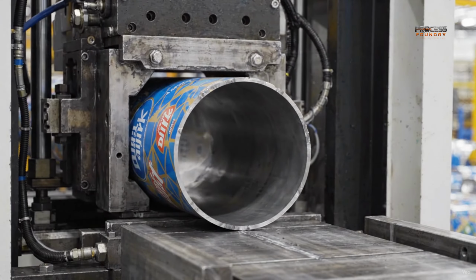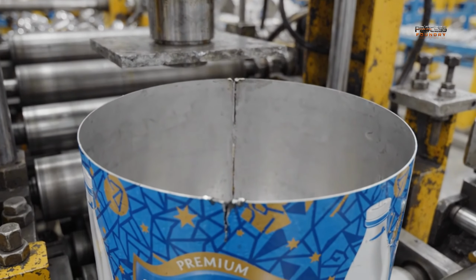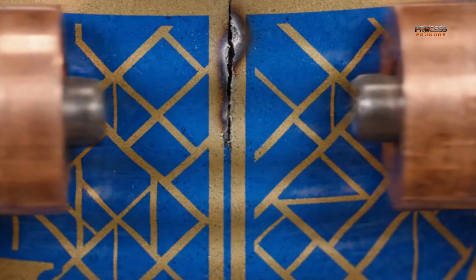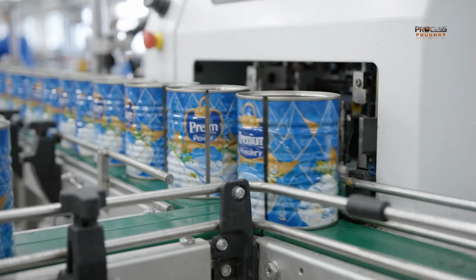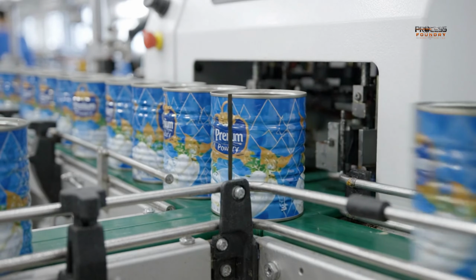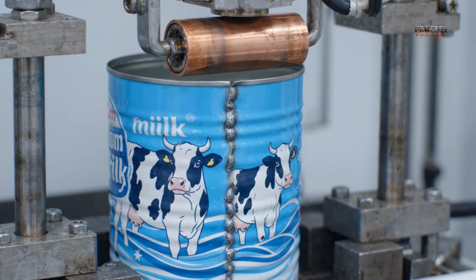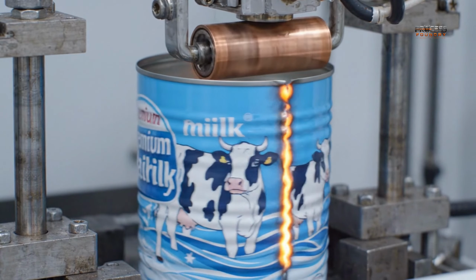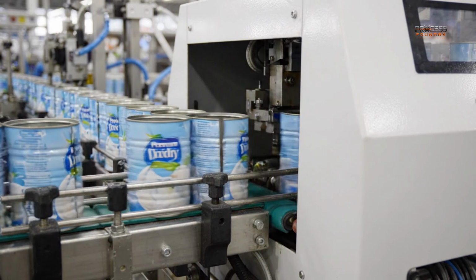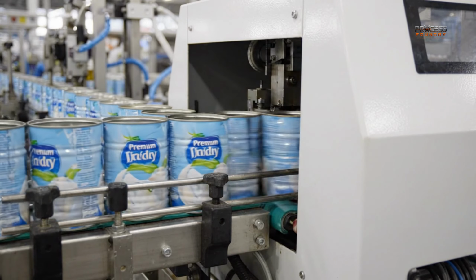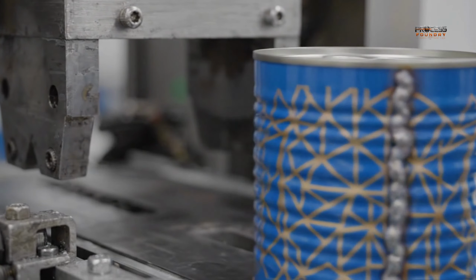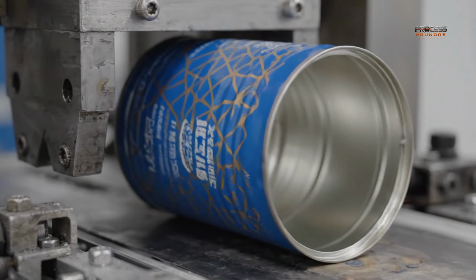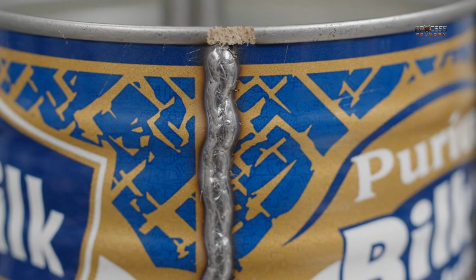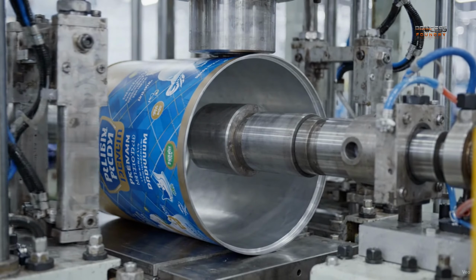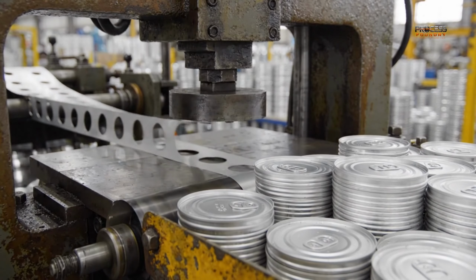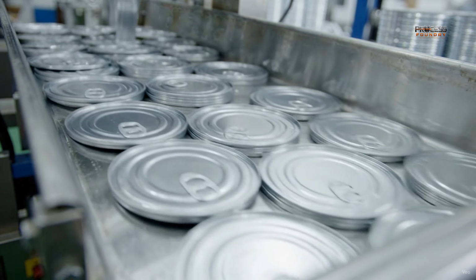Immediately, they are bent and rolled into hollow cylinders. The two steel edges overlap, gliding quickly into a modern soudronic welding machine. Using copper wire resistance welding technology, the contact point is locally heated red, creating an airtight, ultra-thin weld seam without generating any weld slag. The inner gray weld seam is immediately coated with varnish to completely isolate it from the food. At the same time, stamping machines punch rhythmically to create the metal bottom lids.